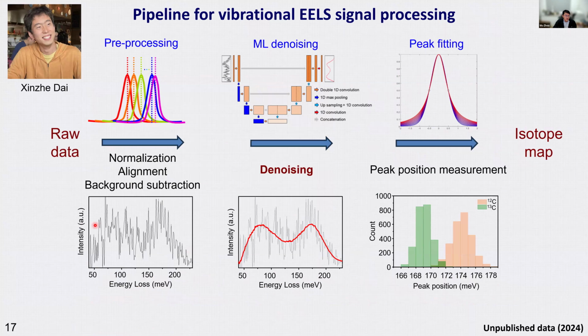And this is very difficult to achieve if you start with spectroscopy data like this. And this is the typical signal to noise ratio we can achieve when we do the mapping. So in order to get to high accuracy in locating the peak position from this level of signal to noise, one of my students, Zhou, who is right now a PhD student at Cornell, developed a neural network to denoise the experimental data. So we start from the noisy data here. After denoising, we can have a reasonably good signal to noise ratio in the spectrum. And from there, we can accurately identify the optical phonon peak position.